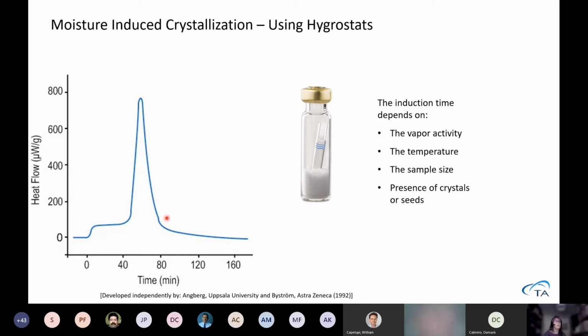But you can also integrate and quantify how much amorphous content I have in the sample. You can see on the time scale here that we get the peak very quickly. This is more or less a 2-hour measurement. This time will depend on the vapor activity. The higher the water activity, the faster the peak will come, because it will more quickly absorb all the water it needs to induce the crystallization.